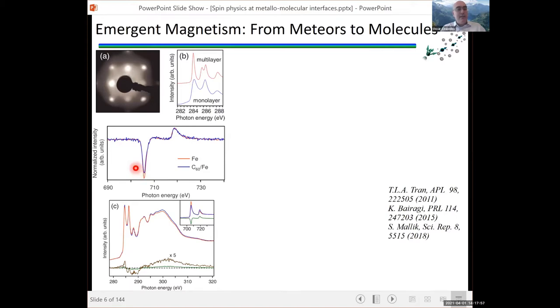There is a difference in the magnetic dichroism of pure iron with respect to C60 on iron. If you look at the carbon edge rather than the iron edge, you also can see a dichroism, which will be a sign of induced magnetization in the C60, now without any metal involved in the actual molecule. But the signal was considerably weaker, so harder to interpret also because you cannot apply some rules to the sigma and pi bonding orbitals of carbon.